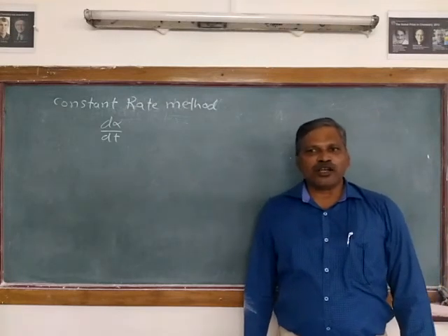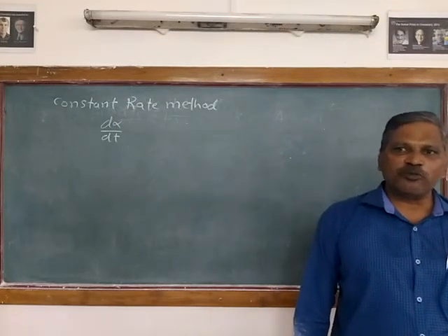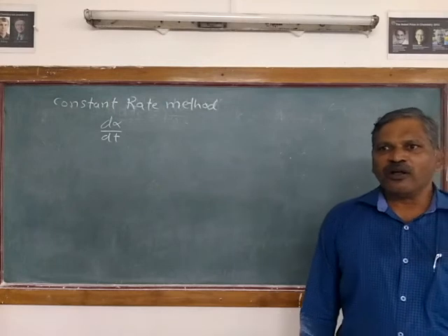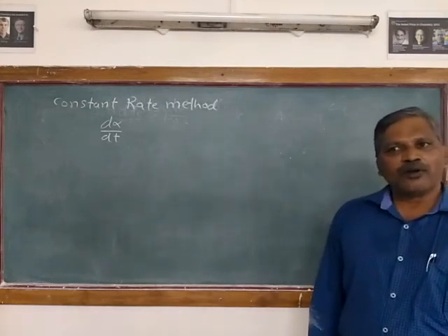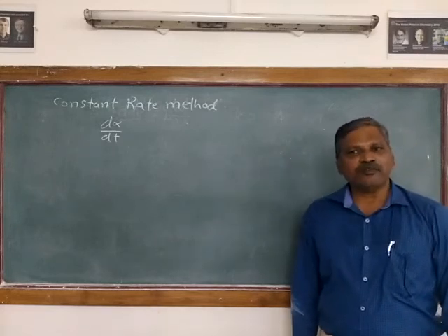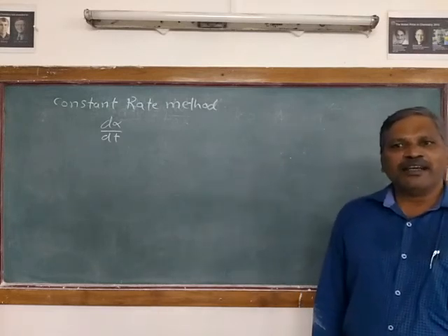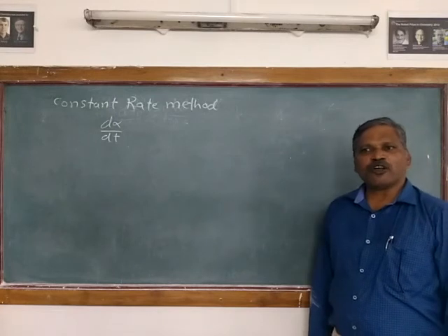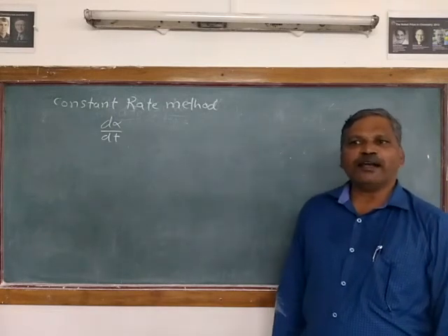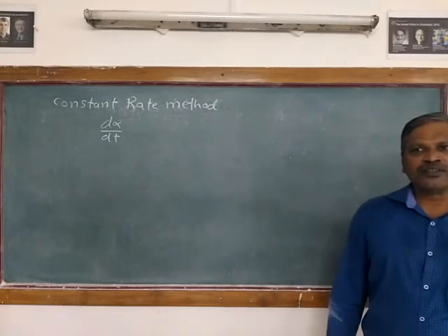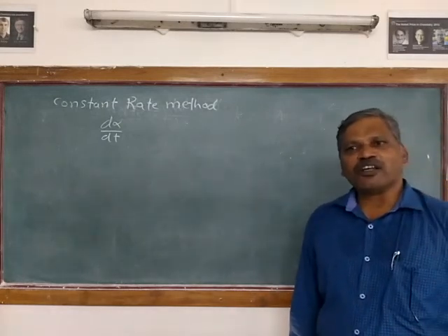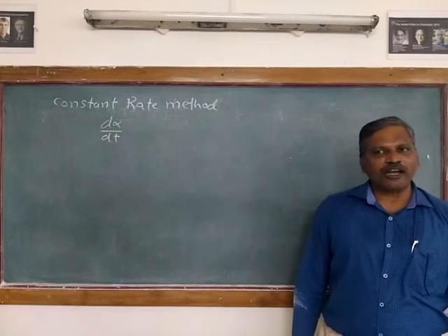The quasi-isothermal, quasi-isobaric techniques of the Paulik brothers control the system in such a way that it keeps the rate of mass loss constant and confines the reaction gases so that they are lost at constant atmospheric pressure.